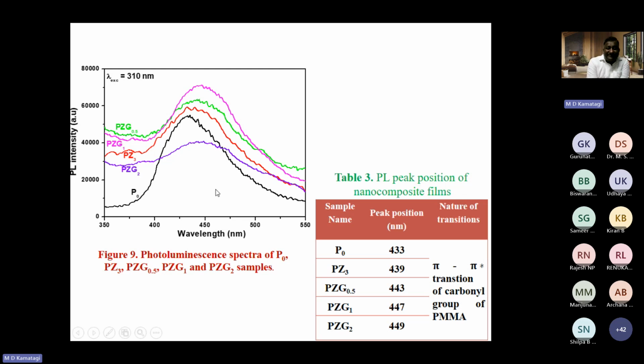Now here is the twist. In the case of PMMA and ZrO2, the photoluminescence properties went on increasing as the ZrO2 concentration increases. This is probably due to the ZrO2 being crystalline in nature, and the interaction of this ZrO2 with the pi transition of PMMA has helped the intensity to go up. But this is not the case with this.